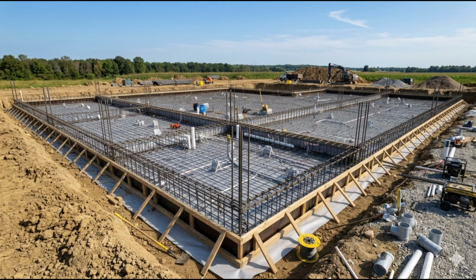Design imposed load, 10 kilonewtons per square meter uniformly distributed. No concentrated point loads. Self-weight, 5 kilonewtons per square meter. Total characteristic load, 15 kilonewtons per square meter. Design ultimate load, ULS 21.75 kilonewtons per square meter. Required reinforcement area, bending 285 mm². Required reinforcement area, crack control 360 mm². Governing, crack control. Actual 28-day compressive strength, mean of 16 cubes 43.3 N/mm². Minimum individual result, 41.7 N/mm². Compliance assessment, pass.